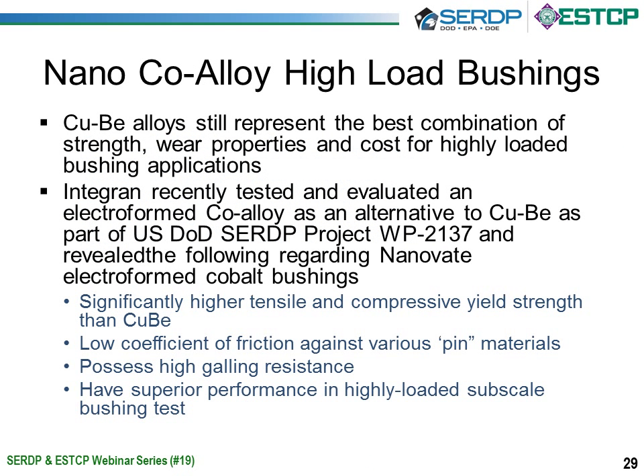In this project, we actually originally looked at developing a high-strength copper alloy for the material as an alternative. Rather than using precipitation hardening, we wanted to use the ultrafine grain size to try to achieve the same strength properties in copper. However, as we progressed in the project, we realized that copper, even with the grain refinement, it's hard to get to those strengths of copper beryllium. So we opened it up and looked at different materials.